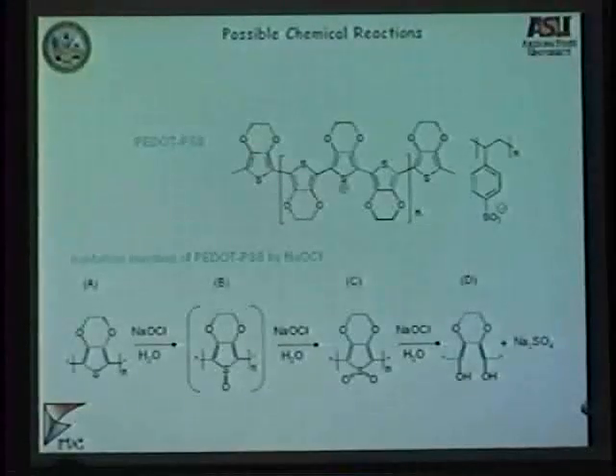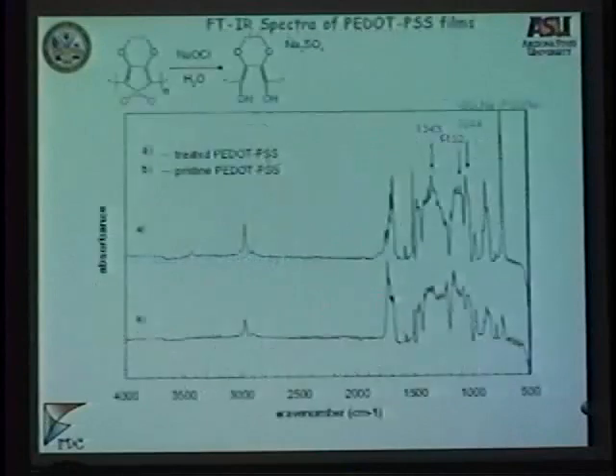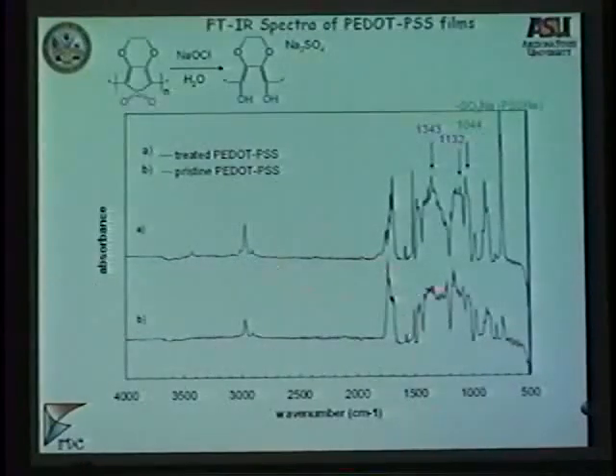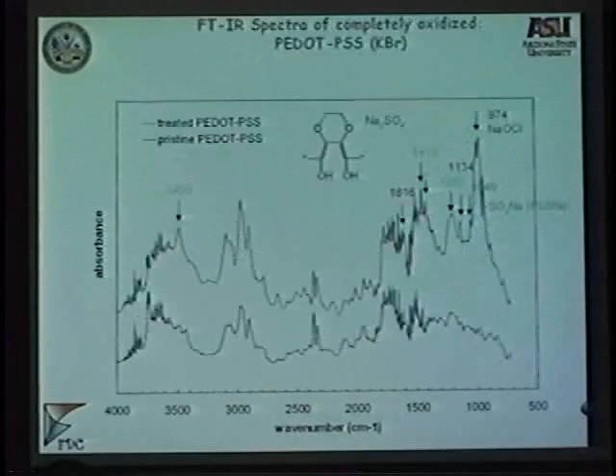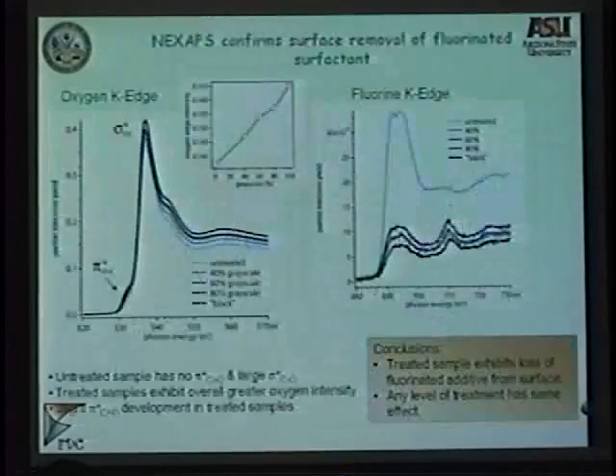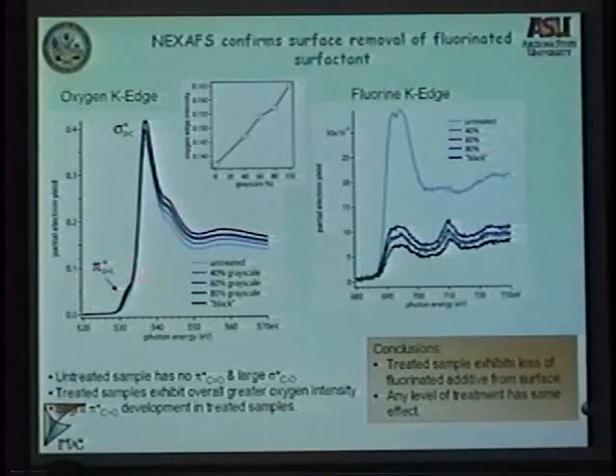If I may spend 1 minute just quickly to say what's happening, we think that the PEDOT is degrading in the following manner. When we do FTIR, we see some new peaks here for these type of bonds generating. But more importantly, recently we did, I'm going to skip the FTIR here, recently we did near-edge X-ray absorption fine